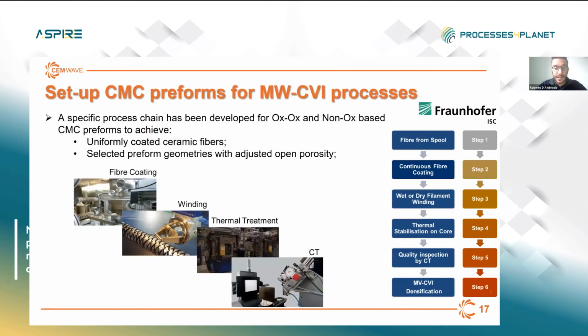Of course, another major task regards the preparation of the CMC preforms for the microwave CVI processes. So a specific process chain has been developed for both categories of material at the Fraunhofer Institute of Bayreuth, developing CMC preforms which were based on uniformly coated fibers and with selected preform geometries with an adjusted open porosity to favor the penetration of the reactive gases during infiltration.